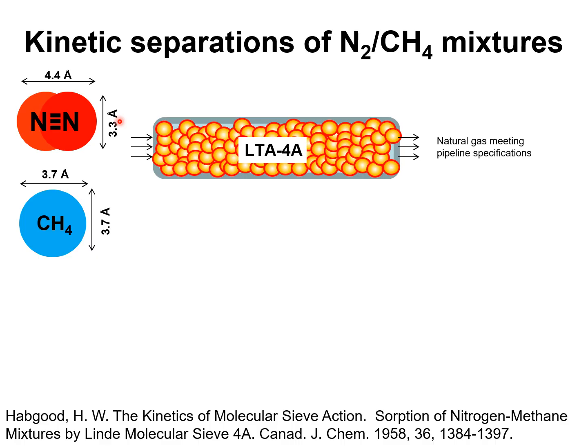It is desirable to use adsorbents and PSA technologies that are selective to nitrogen. However, for most known adsorbents, the adsorption selectivity for nitrogen-methane mixtures is in favor of methane due to its higher polarizability. One practical solution is to rely on diffusion selectivities by using micro-porous materials such as LTA4A zeolite.